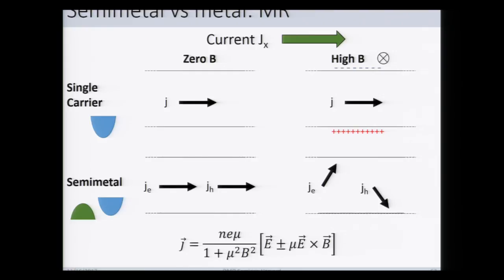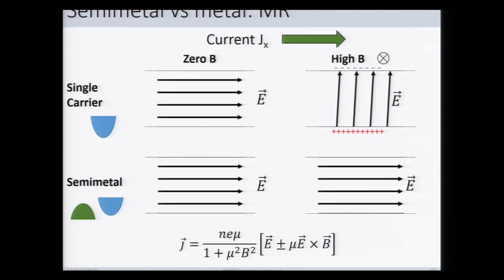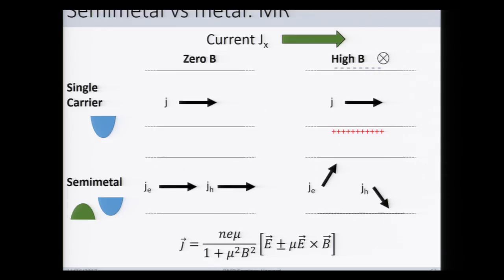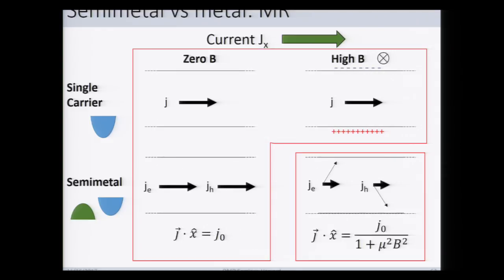Whereas for a semi-metal, your electric field profile is still along the channel with an out-of-plane magnetic field, and you actually have a transverse velocity. And so as a result of this, you can take the component that's along your channel of the local current density of each carrier type, and you get a quadratic suppression that you don't have in the single carrier model.